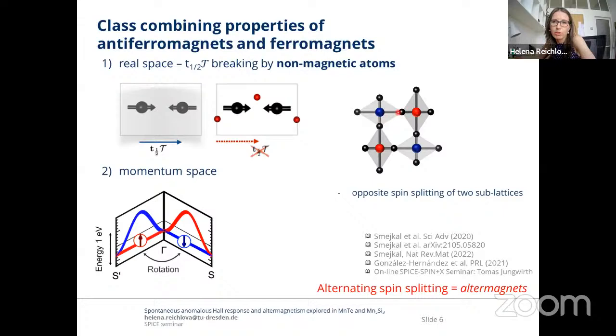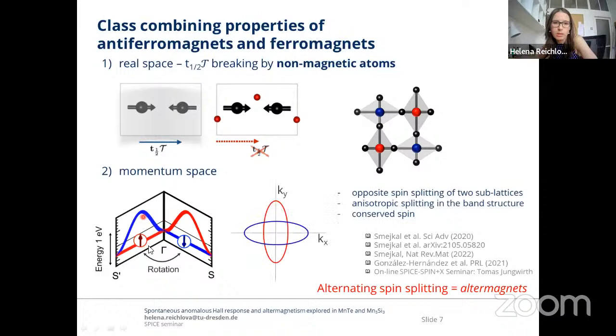And together with this opposite spin splitting of these two spin sublattices, it has consequences in the momentum space, and it demonstrates as a splitting of the spin, which is alternating. So we can see a clear anisotropic splitting in the full band structure. And it's not only small, it can be up to one electron volt. And here, just the energy cuts, which highlight the anisotropic character, and also highlight another likable feature, which is the conservation of the spin. The alternating spin polarization in momentum and real space suggested the name altermagnetism or altermagnets, which I will use in the following in this talk.